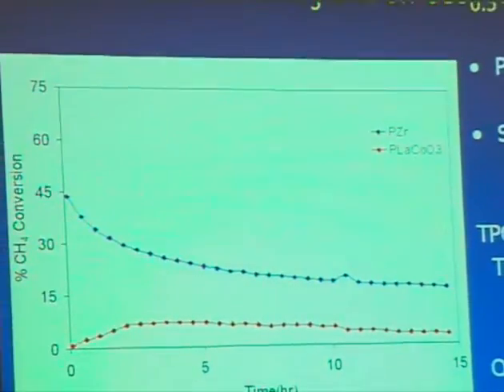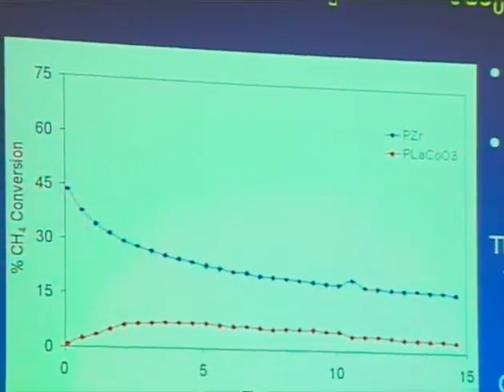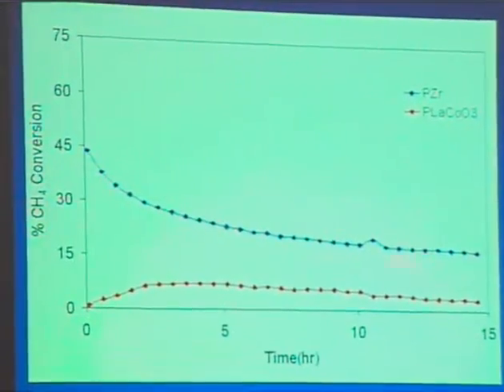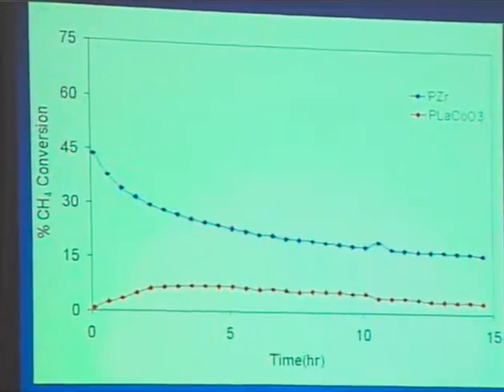Activity studies showed poor performance for the perovskite material and no activity for the strontium iron cobalt oxide. You see an induction period here for the perovskite material followed by a decline in activity, and that induction period could be due to some encapsulation of the metal during the high temperature treatment and reduction. And this has been compared here to the platinum zirconia catalyst that we'll see later.